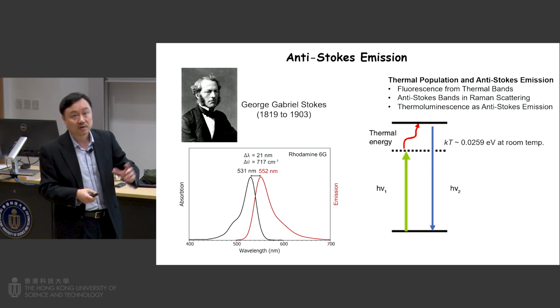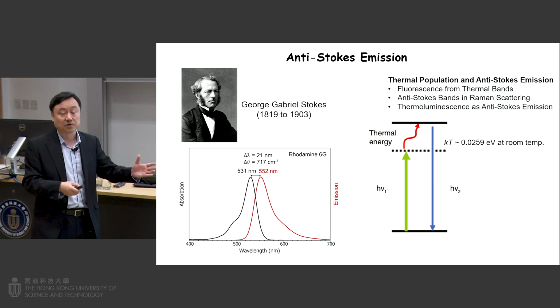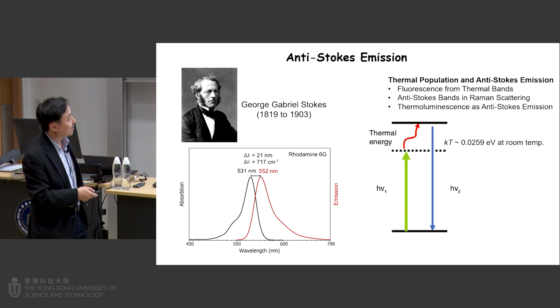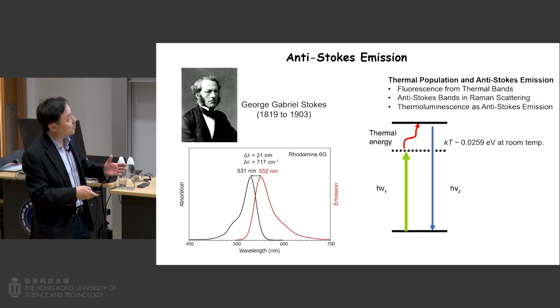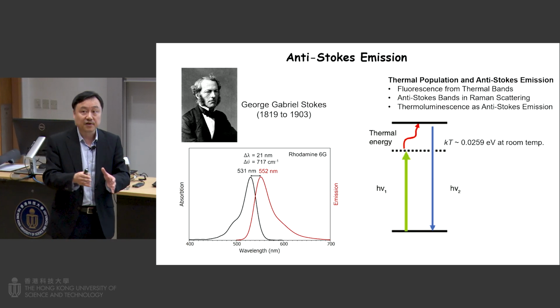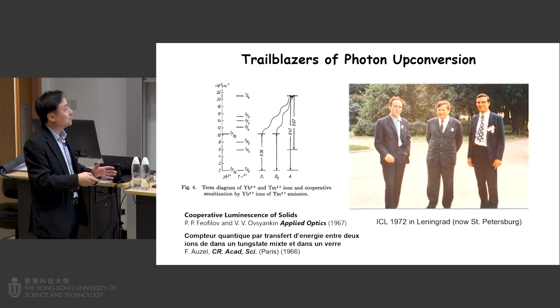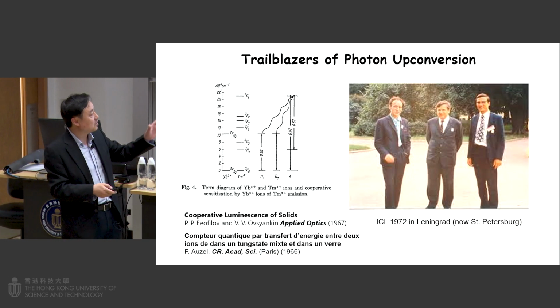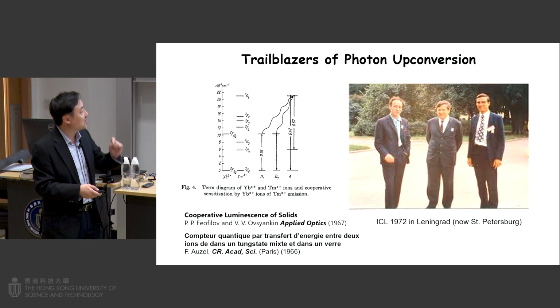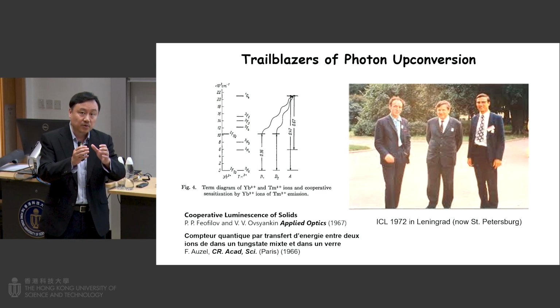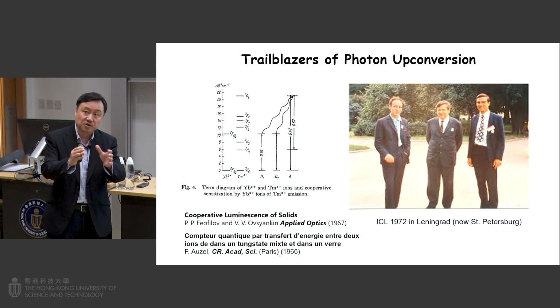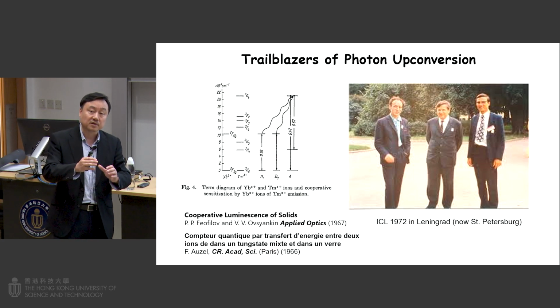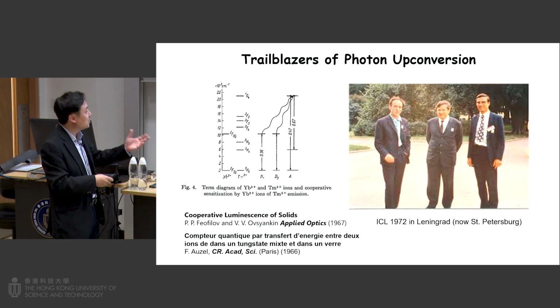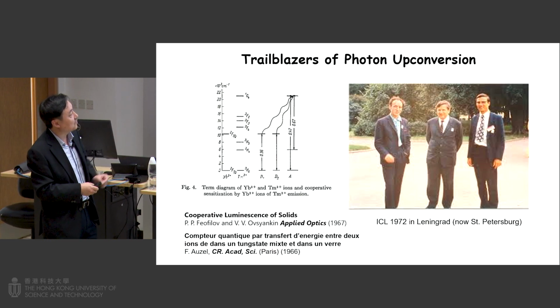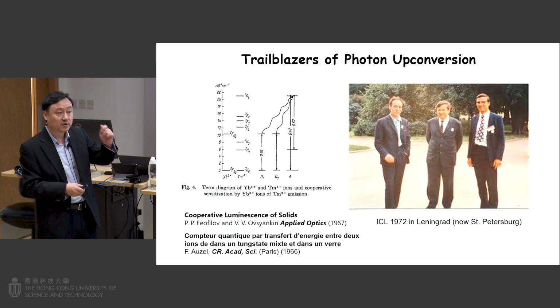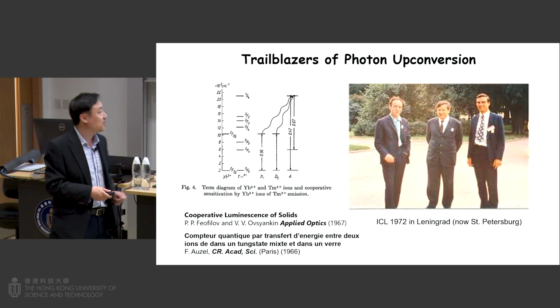It's actually invisible to naked eyes. So sometimes it's very difficult to detect. So how do you solve the problem if you really want a high efficiency anti-Stokes emission? These researchers discovered that using lanthanide ions doped into crystalline structures, for example inorganic crystals like sodium yttrium fluoride, you can actually achieve pretty strong upconversion emission, strong enough to be visible to the naked eyes.